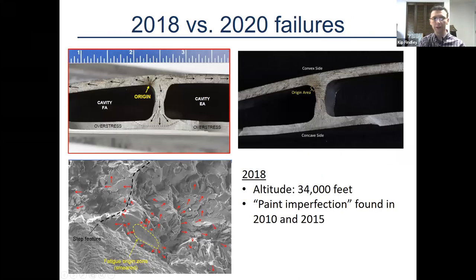Okay, so if we look at these two failures, 2018 versus 2020, sorry, I don't even know what year it is. This is the 2020 blade that we just looked at. This is the 2018 blade. Same thing. You see this beach mark and this oxidized region showing where the fatigue crack grew. It's at a slightly different location, but that, I think, indicates that the stress around this filleted region is pretty comparable. And so a fatigue crack can nucleate and grow anywhere within this region.